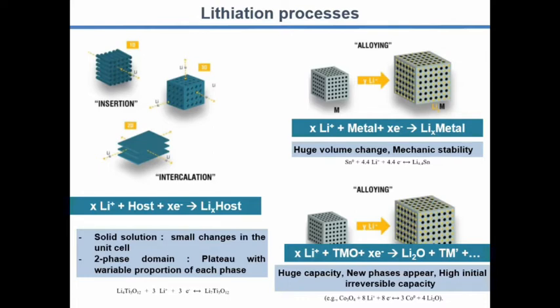The second mechanism is alloying. It is normally seen in the anode side, where sometimes we use some metals as anode, like aluminium or tin or antimony. And we have this alloying. Lithium is forming with this metal some new alloy, lithium metal. We have huge capacity, but the problem is that we also have huge volume change, which can be a drawback for the mechanical stability of the anode material.